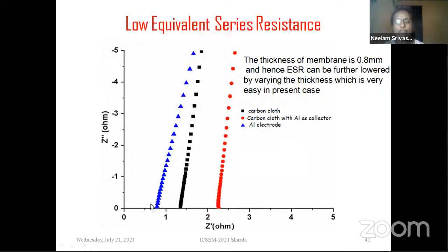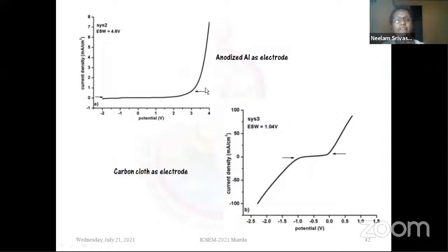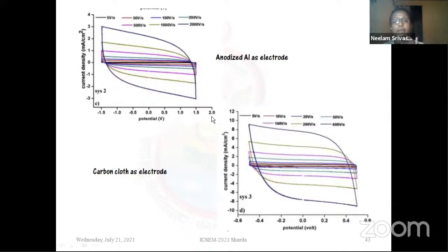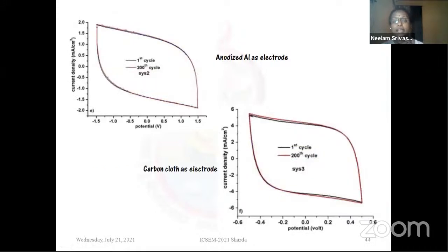So you can see that here also we have got good low resistance. Again, I am repeating that it is for 0.8 mm, and hence please remember, when we target it for commercial application, we can reduce the thickness to a great level, and hence the ESR value will certainly go very low. So from our understanding, it is really a very exciting result for us. And they have shown similar behavior as far as your LSV is concerned, similar to what has been observed with the other electrolyte systems. So it is again a very encouraging result for us. The rectangular behavior has been maintained by these two sets of cell fabrication structures, and the cycling is also very good. We have observed good cyclic behavior.